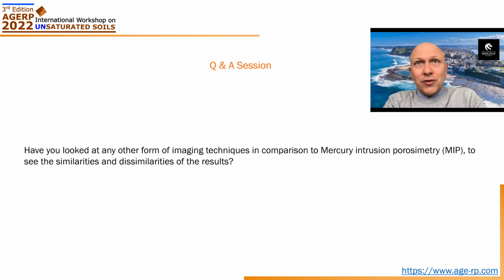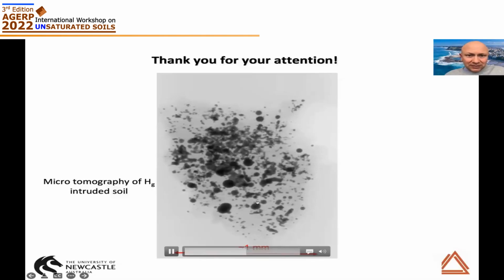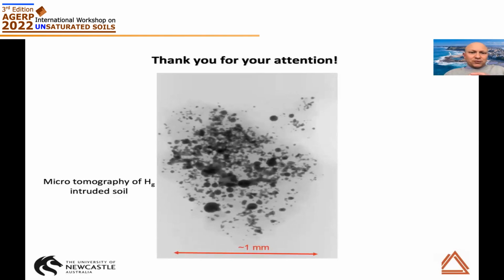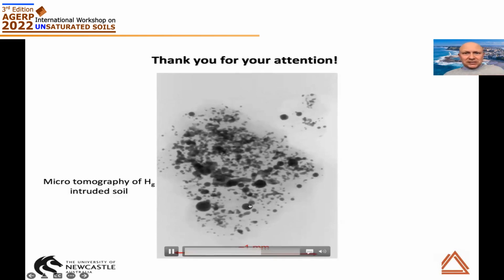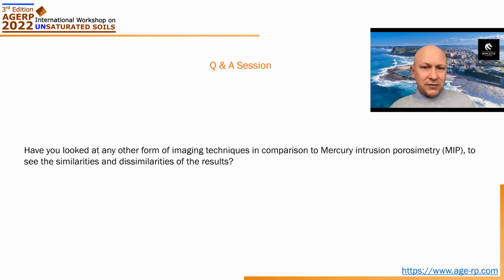And if you want to use tomography to measure pore size, good luck, because the pores are really small, and the contrast between the clay and the air is typically not enough to see anything. That's why we use very small specimens, intrude them with mercury first and scan that, because we thought the mercury would be really, really visible. And in fact, it is. But then you've got the issue that you're basically measuring mercury after having performed the test. If you look at the photo here, you see a lot of beads. When the mercury has been removed, it falls back and forms a bead in a pore. So that's probably in a pore bigger than the bead, and it won't give us exactly the shape of the pore. So it's quite difficult to combine different techniques, or we haven't found a solution. Maybe there is one, maybe somebody has done it, but we couldn't quite do it.